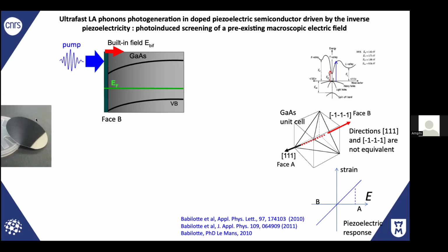When you shine light above band gap, you probe with, let's say, a red of 800 nanometer, and you pump with 400 nanometer. So you create electron-hole pairs near the surface, and basically these electrons and holes are accelerated in that built-in field and screen that field. If they screen that field, then through the inverse piezoelectric effect, they force the lattice to relax from a mechanical point of view and emit coherent acoustic phonon pulses.